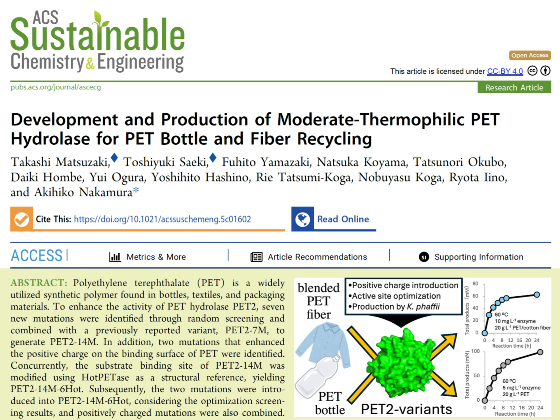It really was. This meticulous, multi-step engineering process led to the creation of PET2-21M, a variant with an incredible 21 mutations in total. 21 mutations. And the performance? Truly remarkable. It demonstrated a 28.6-fold increase in the concentration of total product compared to the original wild-type PET2. 28.6 times. That's huge. It's a massive increase.